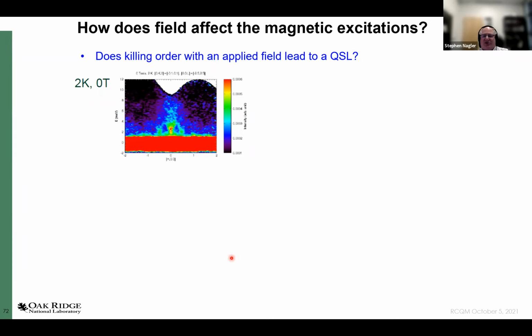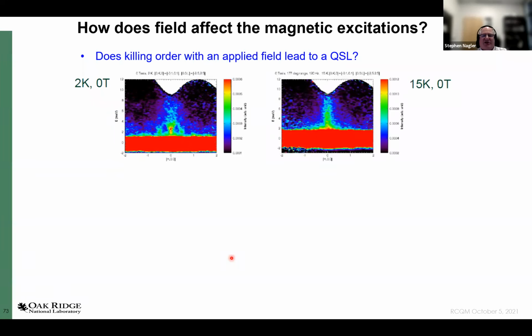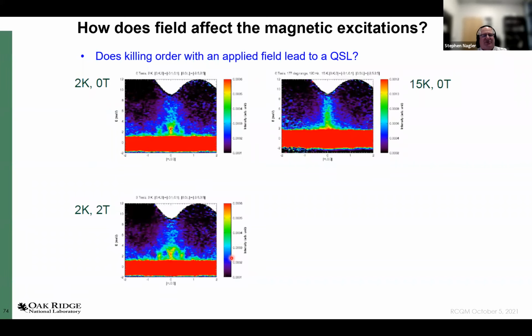So what about this applied field that kills the order? Well, here's what I see at 2K and 0 Tesla. And again, here's 15K and 0 Tesla. If I put on a small field, actually, the spin waves that I measure get stronger. This is because of a domain repopulation effect and how the neutron scattering cross-section works.